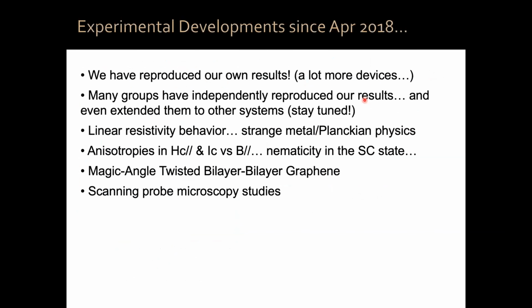Another thing that we have seen, and I'm only going to list here, is linear resistivity behavior, which is reminiscent of the strange metal and Planckian physics that takes place in many correlated materials. We have measured anisotropies in the critical magnetic field and critical current, which are indications of nematicity, spontaneous breaking of rotational symmetry in the superconducting state of the system. We have looked at other systems, for example, magic angle twisted double bilayer graphene, so 4 layers twisted pairwise on top of each other. They have very interesting correlated physics. A lot of scanning probe microscopy studies, first STM, has happened.